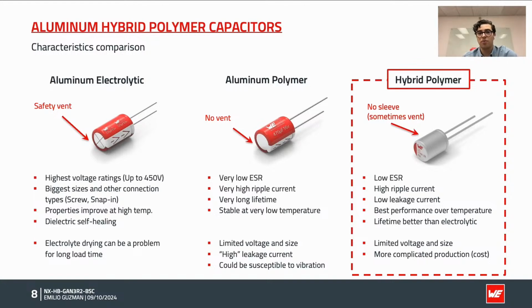And now switching to the hybrid polymer, here we see the best of both worlds in the combination. And so we see a low ESR, maybe not as low as the polymer, or sometimes even lower than the polymer. It has high ripple current, it has low leakage current, and it has the best performance of the three over the temperature range. Also, the lifetime is better than the electrolytic, but it has some limited voltage and size, and it has a more complicated production, thus incurring a bit higher cost.